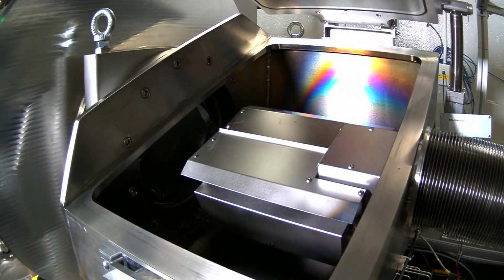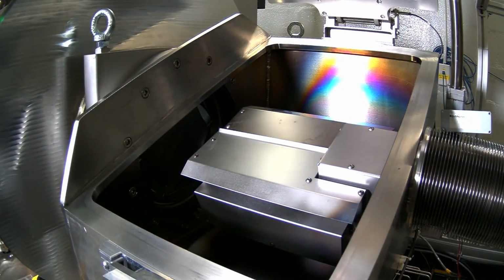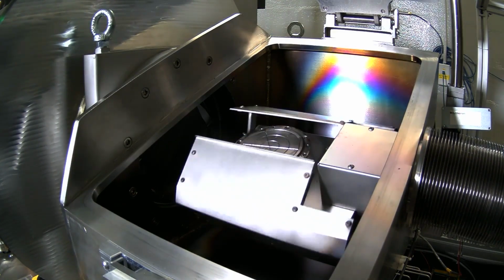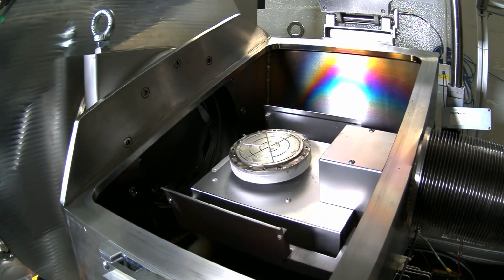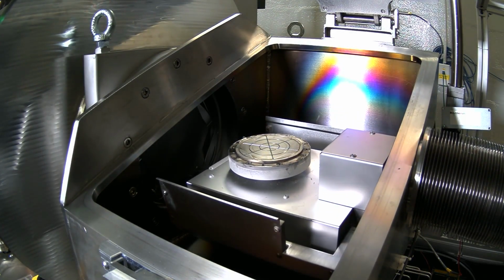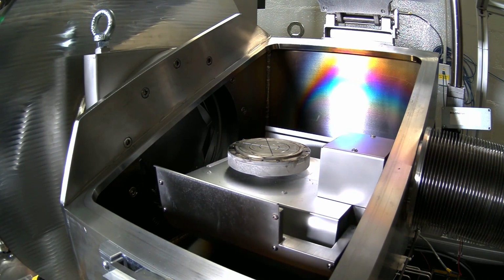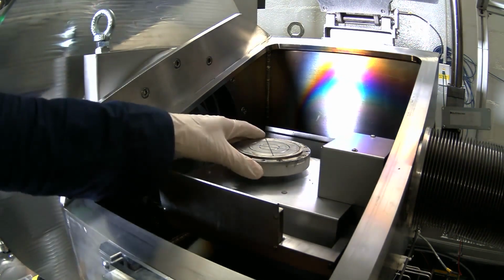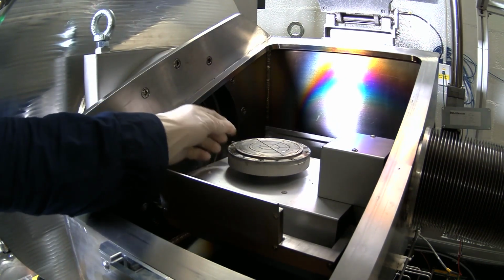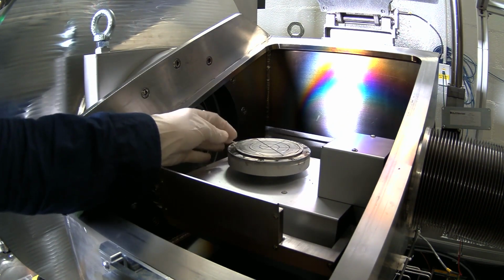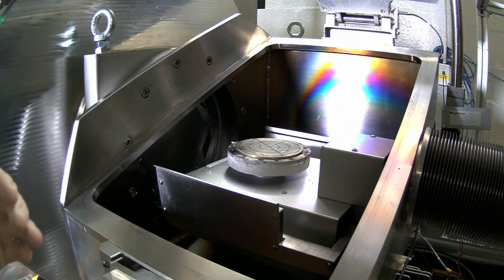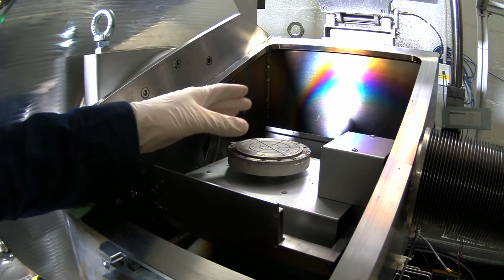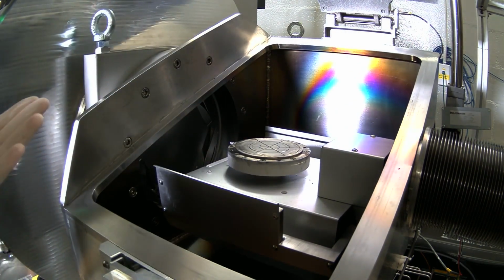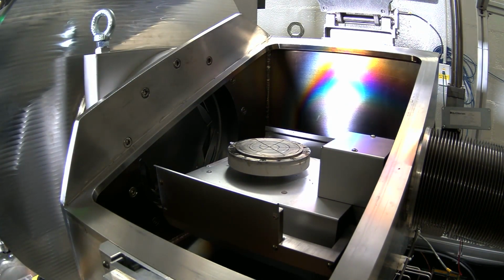So when the door opens, the chuck is actually tilted at 22.5 degrees, because that's the angle it needs to be inserted at into the chamber. So it'll come back to be flat, and now it's ready to load. There is an option where you can load your wafer and hold it down with vacuum while you attach your clamp ring, but I'm not going to use that today.